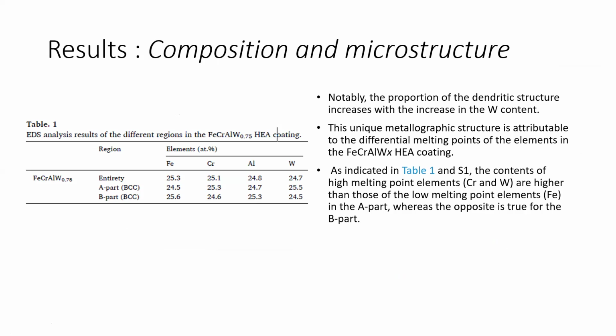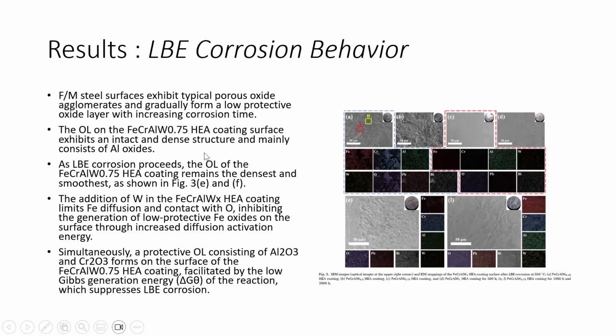So, from table 1, we can see the proportion of the dendritic structure increases with the increase of the tungsten content. And this unique microstructure is attributed to the different melting points of the elements in the ferrochromium aluminum tungsten coating. From this table 1, the contents of high melting point chromium and tungsten are higher in the A part, whereas the opposite is true for the B part, with iron higher.